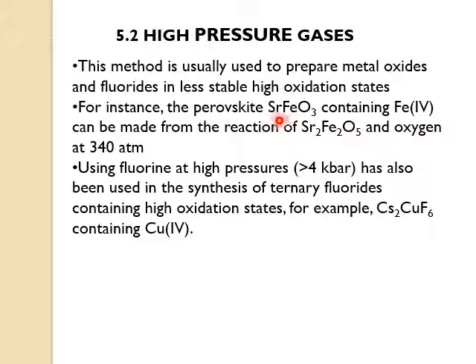For instance, the perovskites, that is strontium iron oxide containing iron 4, because iron normally exists in iron 2 and iron 3 form. This iron 4 form is a very unstable oxidation state of the iron. So for preparing this unstable oxidation state of iron, we can use this high pressure gases method. This synthesis, perovskite strontium iron oxide synthesis, can be made from the reaction of distrontium diiron pentoxide and oxygen at 340 atmospheres. A high pressure is applied, and what are the reactants? Distrontium diiron pentoxide and gaseous oxygen.